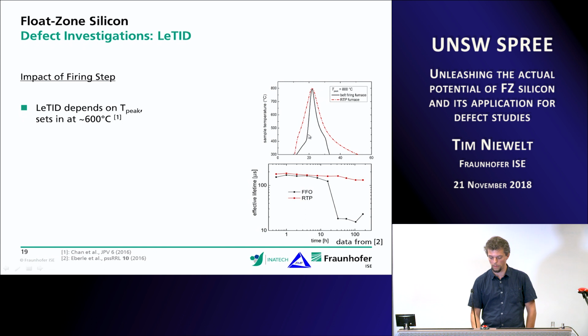One, the black one, is a typical belt firing furnace profile that could also be used in the photovoltaic industry. And the red one is a profile that we generated in an RTP furnace. We wanted to simulate the exact same profile there initially, but the RTP process wasn't fast enough. So we compared what the samples are doing after these two different treatments with the same peak temperature.